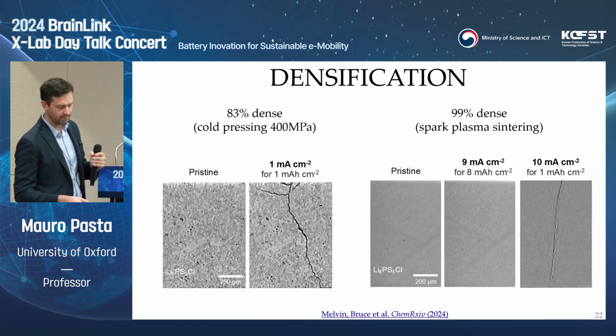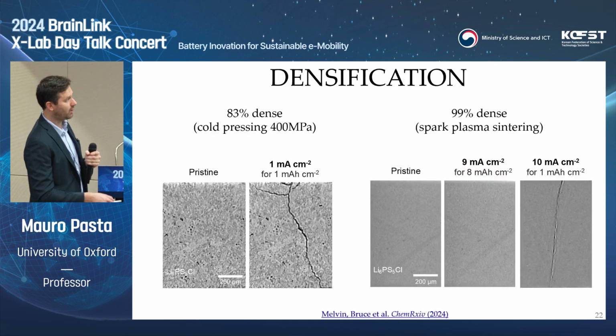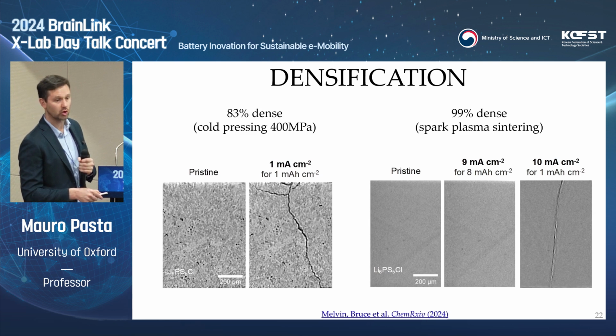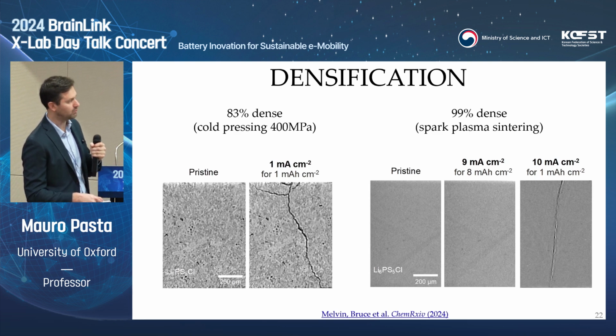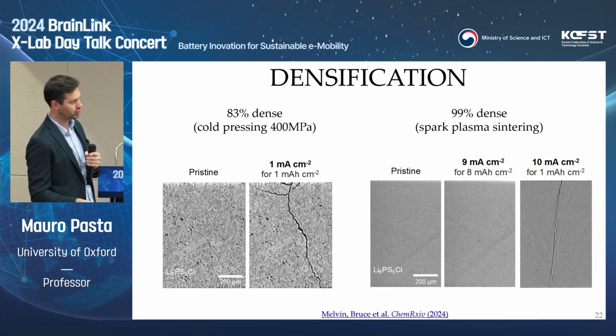So what is the solution then? Well, if you can fully densify, that would be ideal. And we now have evidence. On the left-hand side, you have an 83% dense solid electrolyte, densified by cold pressing at 400 megapascal, which is a very high pressure. But even in this condition, you see your solid electrolyte is quite porous, and 5 microns of plated lithium at a 1 milliamp per centimeter square current density is enough to form a crack, and therefore shorting. While here on the right-hand side is a 99% dense pellet obtained using spark plasma sintering. And as you can see, at 9 milliamp per centimeter square, with 8 milliamp hour per centimeter square plated, so 40 microns of lithium, you still have your fully dense electrolyte, no cracking, no short circuiting.